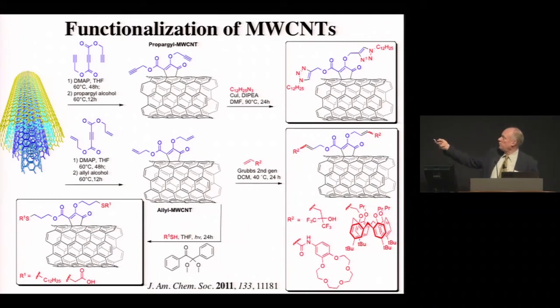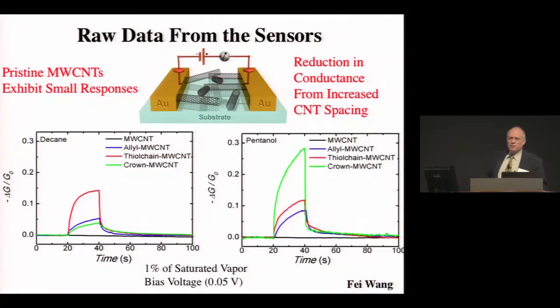And once we have those, we have 2 functional groups per unit. We can do chemistries like the famous click reaction. We can do cross-metathesis chemistry using Bob Grubbs' catalyst here, or we can do free radical additions across these alkenes. And so I just want to draw your attention to the one that's a long hydrocarbon right down here, where we can hang long hydrocarbons, make a very hydrophobic one, and also this one where we now put this hydrogen bonding group. And when we look at those different functionalizations in our sensors, you can see that they behave as expected.